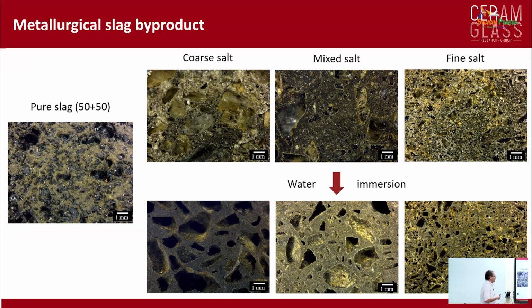And we can also play a little bit more with the system. For instance, if you want to obtain a porous component, you can add something that can be later extracted and recuperated. So we added salt particles, and the salt particles do not dissolve quickly enough when we print, so they remain embedded in the printed material. Then after water immersion, the salt can be dissolved and recovered. You could think of doing this also with sugar, but sugar inhibits the geopolymerization reaction.